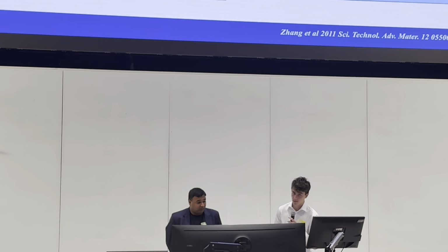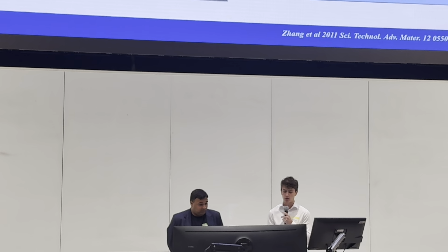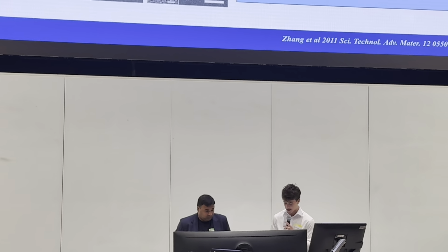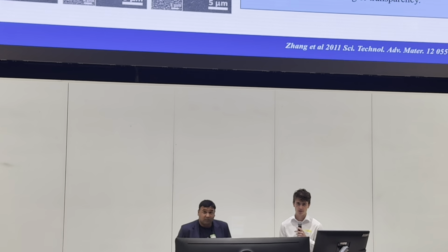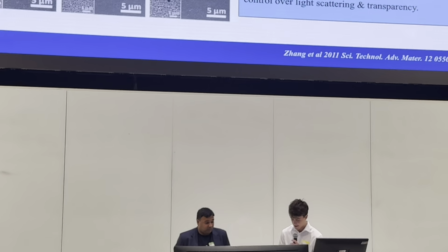Oxygen vacancies can also create electron traps. When electrons fall into them, they emit light, often in the UV range, which is useful for luminescent and optoelectronic devices. At the same time, dopants and grains can be tuned to adjust light scattering and transparency, which is especially important for applications such as dental ceramics where aesthetics take priority.